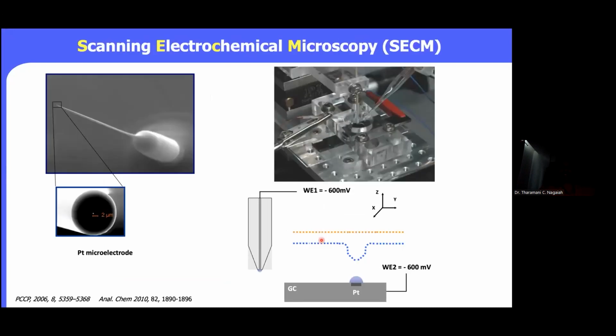What we did here is a similar approach, but since it is scanning probe microscopy, instead of a 3-electrode system, here it's a 4-electrode system. That means we are introducing the platinum microelectrode. You can see that this is the electrochemical setup that we have here. This is a glassy carbon, that means a sample of our interest can be placed on this one.